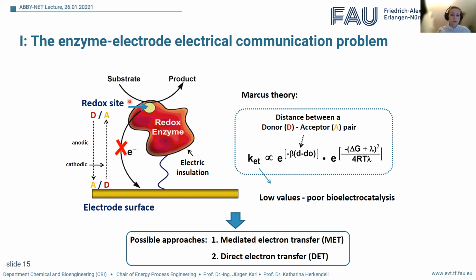So basically, you have a typical donor-acceptor interaction, and this is usually blocked for most enzymes. This can be explained by the Marcus theory of electron transfer, saying that the electron transfer rate is exponentially dependent on the distance between the donor and the acceptor. Most enzymes are up to 10 nanometers thick, and this can be too large a tunneling distance to interfere. So the thermodynamics would enable the redox reaction, but the kinetics would make it so slow that nothing would happen in real life.